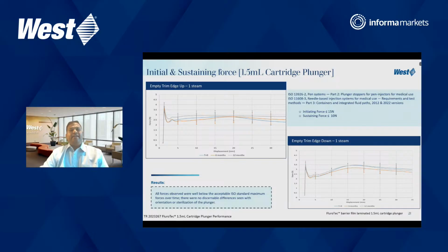You can see the actual data with the trim edge up with 1x steam on the left side for a period of 12 months, and on the right side the trim edge down for 1x steam. If you refer to the ISO, the initiating force limit is not more than 15 Newton, while for the sustaining or gliding force, the limit is not more than 10 Newton. On the left side, the break loose force or initiating force is around 3.5 to 4 Newton in both cases, while the gliding force was hovering around 2.5 to 3 Newton. In both cases, whether trim edge up or trim edge down with 1x, we have seen there are no discernible differences between orientation or 1x or 2x steam sterilization of the plunger. So the results are well within the range and consistent.